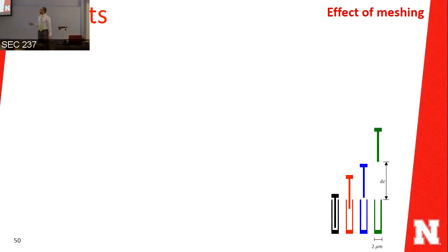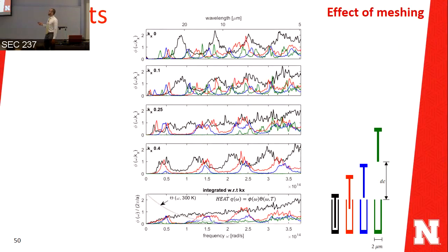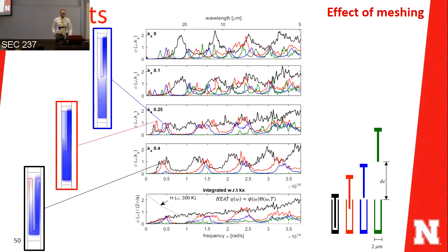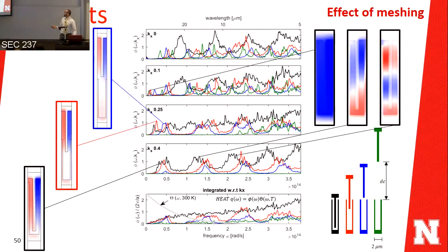To see the effect of meshing, we simulated those 4 cases with different meshing or different separation gaps, and that's the transmission factor at different kx values. You can notice that the fully meshed case has peaks that are higher than all other cases. And the continuum I showed you in the dispersion relation is very obvious here in the integrated transmission factor. There are no values here for this meshed case. If you compare it to the other cases, they have values here at those frequencies. Those are the modes that can propagate in the material in those cases.